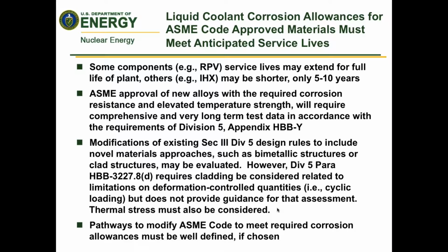If you can't make it with the existing 5 materials under the service conditions that are identified for these plants, and you take the tack that you're going to want to try and approve some new alloys, you have to realize that very comprehensive and long-term testing is going to be required to do that. And the requirements for this are laid out in the new Division 5 Appendix HBBY, which has been published in the last 2 or 3 years, and anybody can take a look at it. The requirements are substantial.